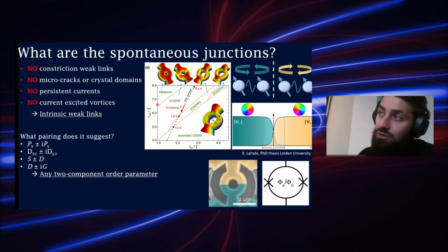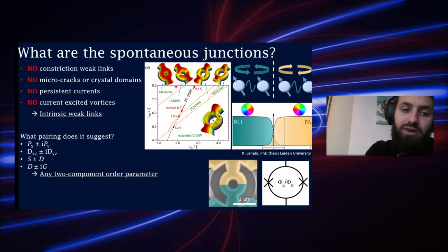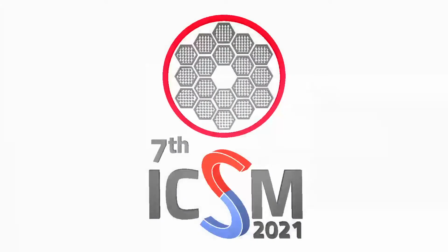There's also a part of the phase diagram we tried to probe where there shouldn't be any junctions. However, we found while making these samples that the necks of the ring can actually also act as Josephson junctions. So indeed, there can be a few junctions or just one, really depending on geometry and temperature.